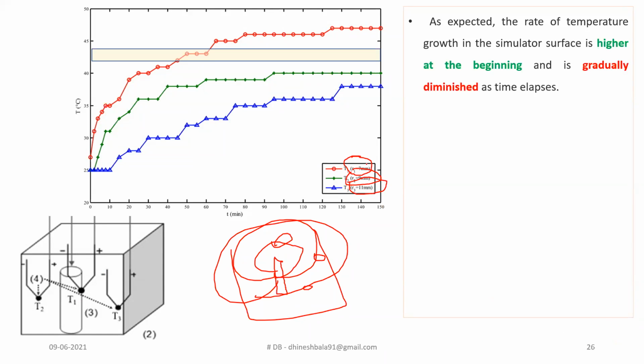And what is the impact of the phase change material with respect to the charging and discharge cycle has been noted out. So as expected, the rate of temperature growth at the simulator surface is higher at the beginning and gradually diminishes as time elapses, because the conversion of solid to liquid occurs in a similar fashion when you are introducing a phase change material closer to the battery.